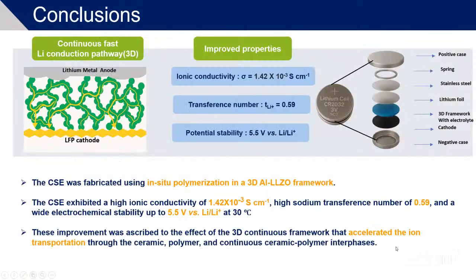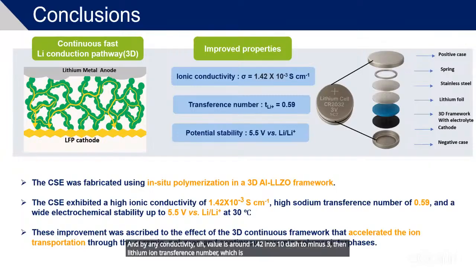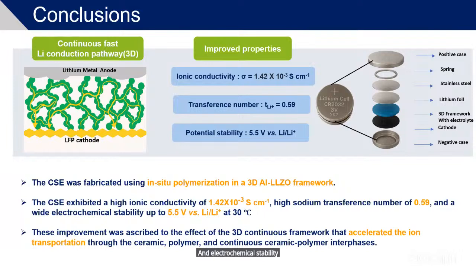So finally, the conclusion. The composite solid polymer electrolyte was successfully fabricated, and the ionic conductivity value is around 1.42 into 10 raised to minus 3. Then the lithium ion transference number is 0.59, and the electrochemical stability is around 5.5 volt. This is the coin cell fabrication.